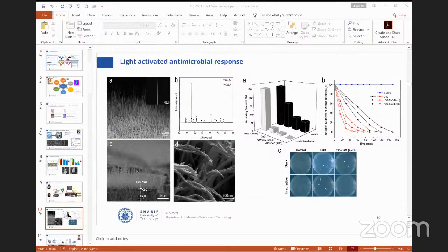As you know, copper oxide is also light active, and then we conformally coated it with graphene oxide layers, as you see in figure D. And then we examined the antibacterial activity under light and without light. And you see here in the middle figure that the materials containing nanorods with a conformal coating of graphene oxide show extremely active antibacterial effect. The red line in the graph on the right side.